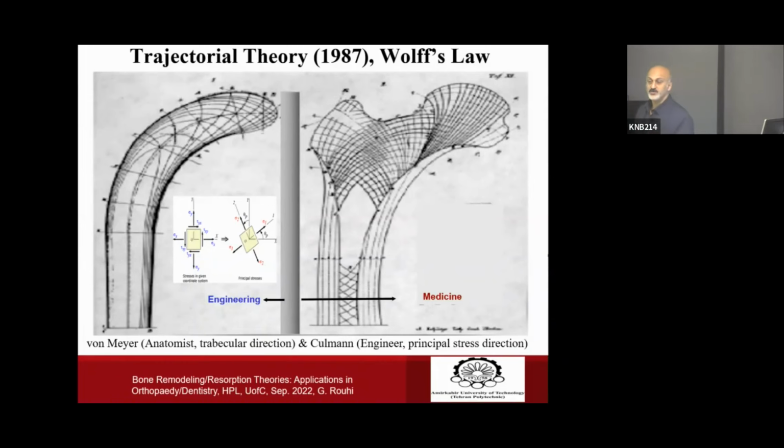I'm sure based on what I've explained about Wolff's law, you think about why this happens from, let's say, a mechanical point of view. If I increase the load, the thickness of trabeculae would increase. If I decrease the load, the thickness would decrease. So the density would decrease. So the modulus of elasticity would decrease. So the strength would decrease. Why? Let's think about a thermostat.